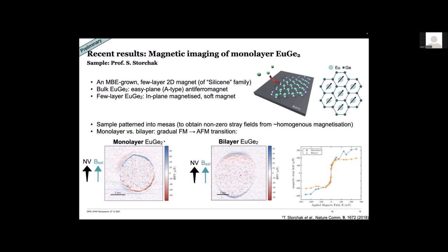If you look closely, and that's maybe one of the values of this being a quantitative method, you see that actually the monolayer appears to be more strongly magnetized than the bilayer. But the bilayer does not give zero magnetization. So it's not the same thing as we saw before with chromium triiodide, where you have just antiferromagnetic stacking. Somehow this material, conversely to chromium triiodide, seems to transition more gradually from this ferromagnetic coupling in the few layer limit to the antiferromagnetic coupling in the many layer or bulk limit. So this is something we're currently trying to understand.